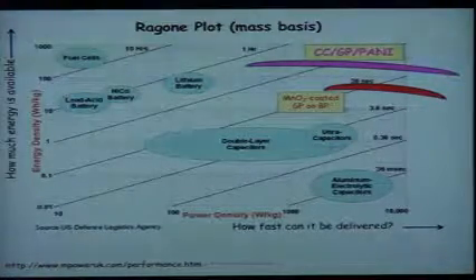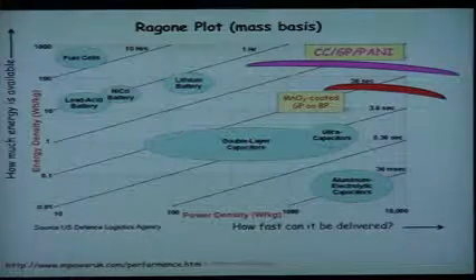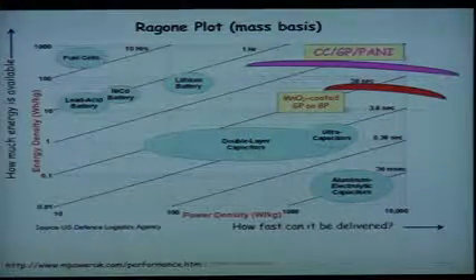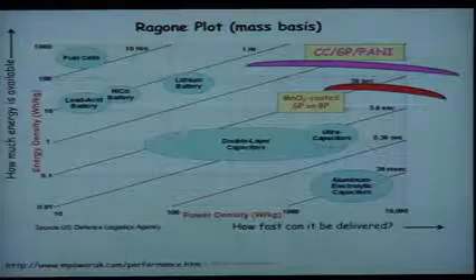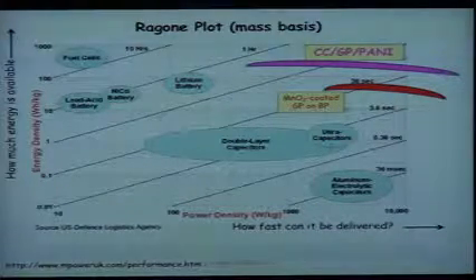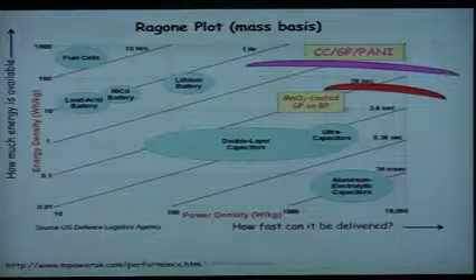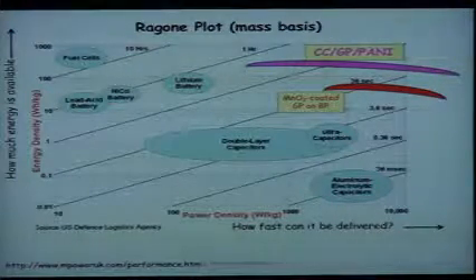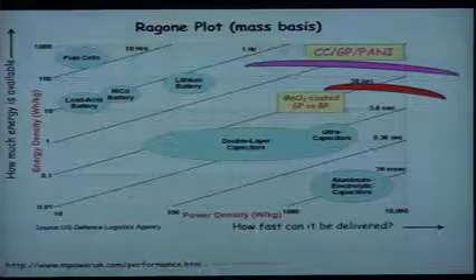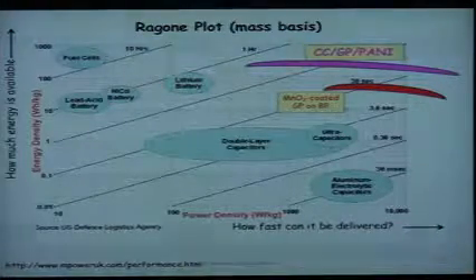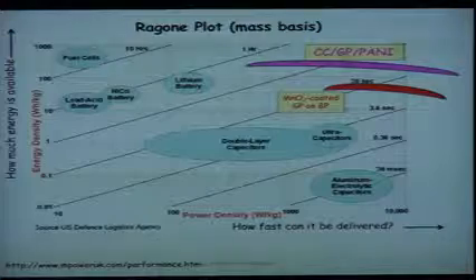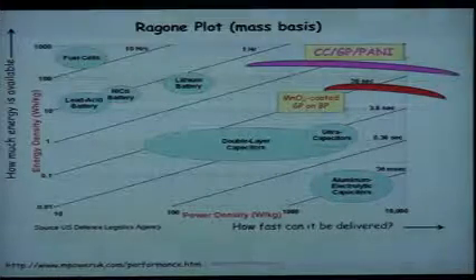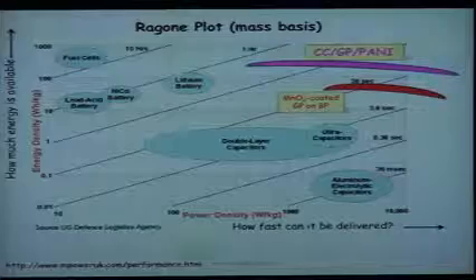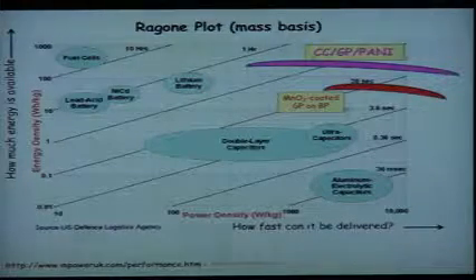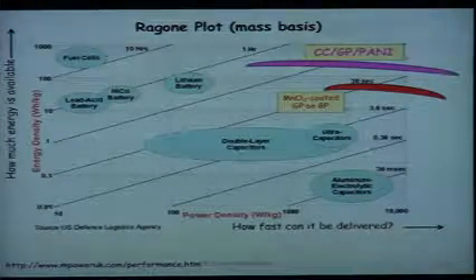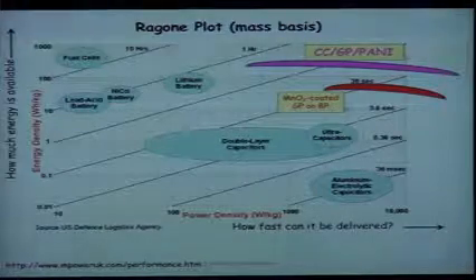All right? And so in looking at this, if I have low energy density, then it would take only a short amount of time to fully discharge that device. So it's a useful comparison. And so we look at this and we see the batteries here are in the hour range for the duration to fully discharge them. Lead acid battery. Lithium ion is a little bit better than the others, but lithium ion has higher energy density than other batteries typically, and higher power density. That's why it's so popular.